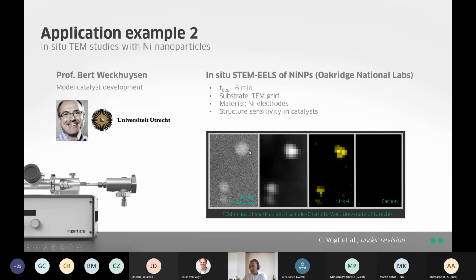From the HAADF-STEM image, you can see we have these bright spots, and using STEM-EELS, you see that it's a nickel core, and these nickel nanoparticles are completely free of any carbon contamination, which is then the unique part about preparing these nanoparticles in the gas phase.